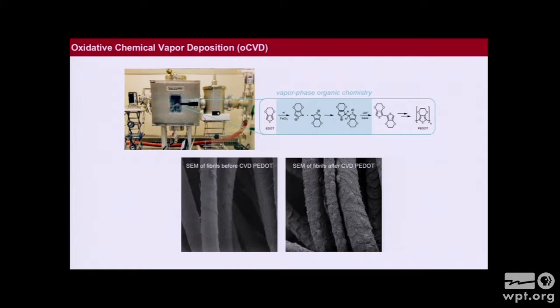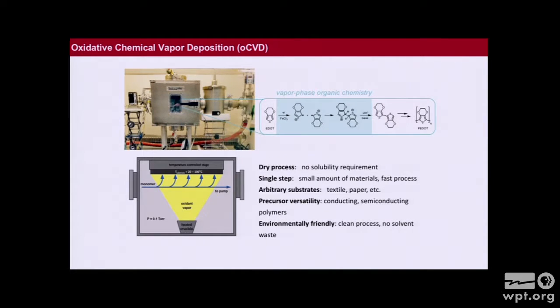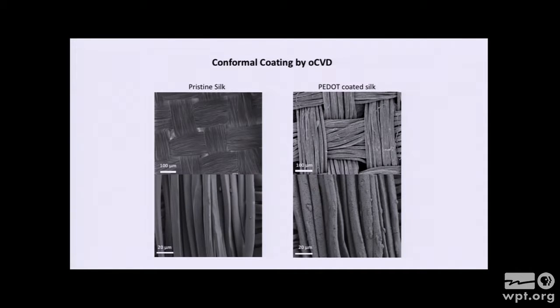Okay. So whatever fabric sample we put in this chamber, in this mixing region, we get completely conformal deposition simply by tweaking a few knobs and basically changing the monomer flow rate and the vacuum of our chamber back here. And so what you can end up doing is get over those multiple levels of roughness that I just told you would absolutely preclude the formation of electronic substrates or devices on a fabric substrate.